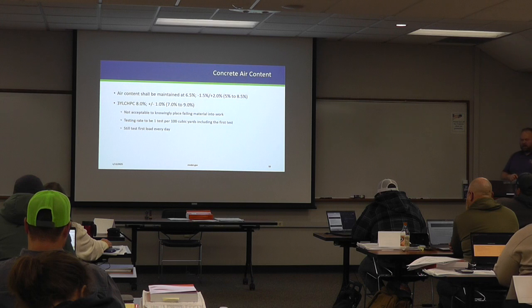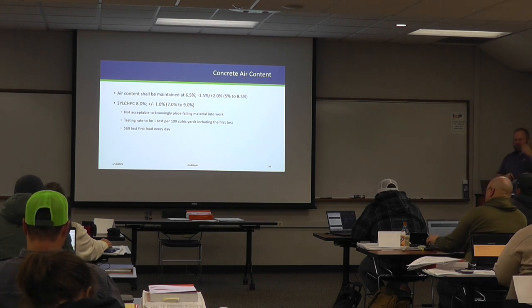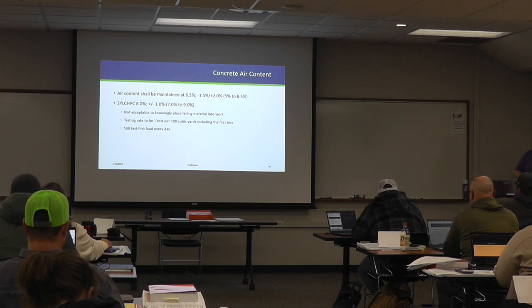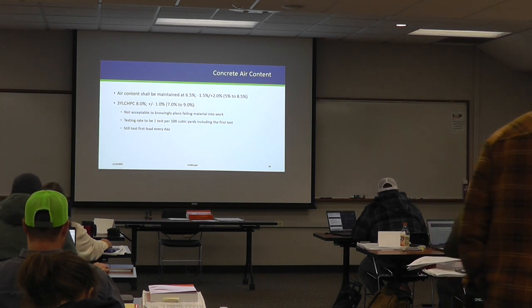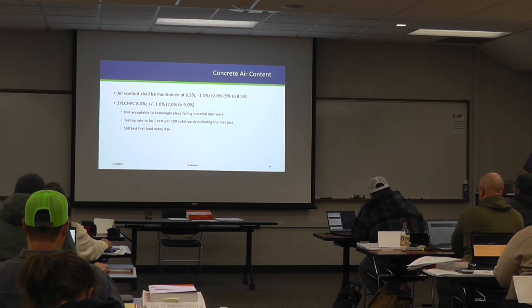And so if you are taking an air test and you get like a 5.1, technically you can accept that concrete, but you should probably let the contractor or the ready-mix producer know that they need to increase the air content to get as close to that 6.5% as possible.